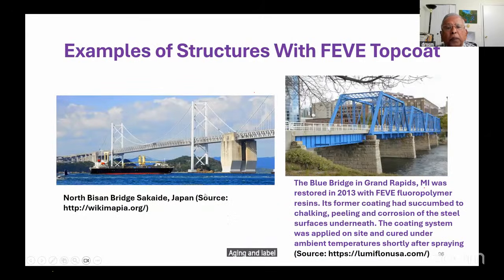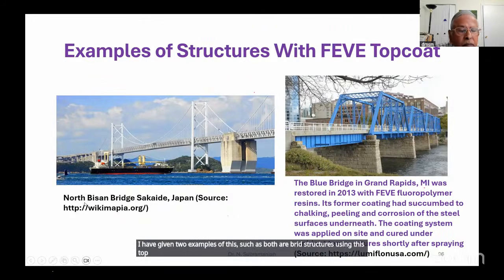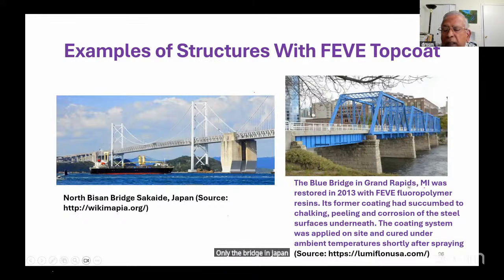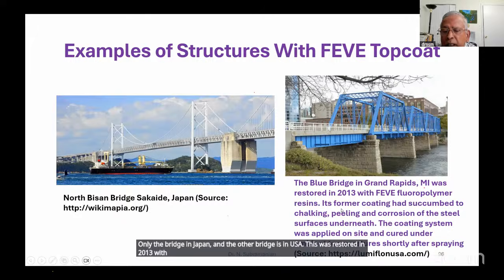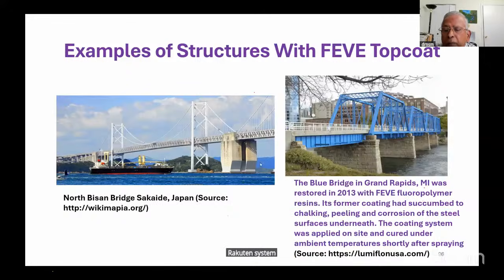I have given 2 examples of these structures. Both are bridge structures using this top coat. One is a bridge in Japan and the other bridge is in USA. This was restored in 2013 with FEVE resin. Its former coating had crumbled due to chalking, peeling, and corrosion of the steel surface underneath. The coating system was applied at site because it's an existing structure, and cured under ambient temperature shortly after spraying.